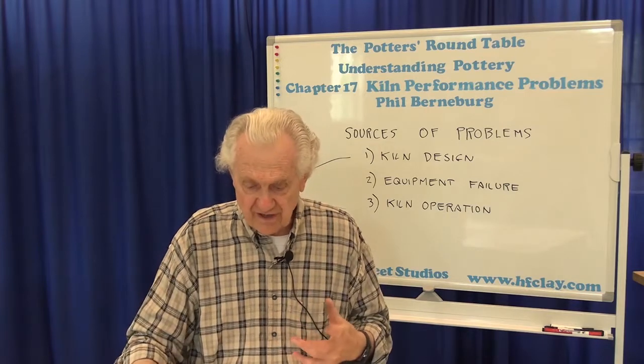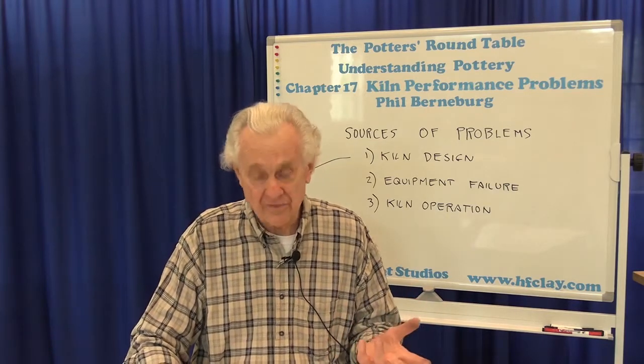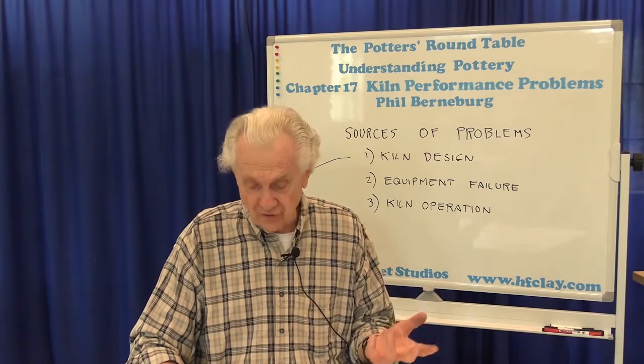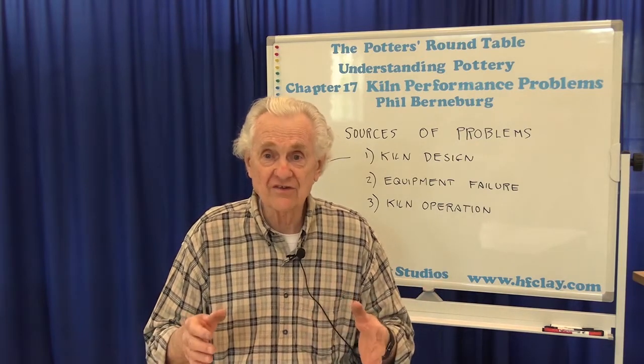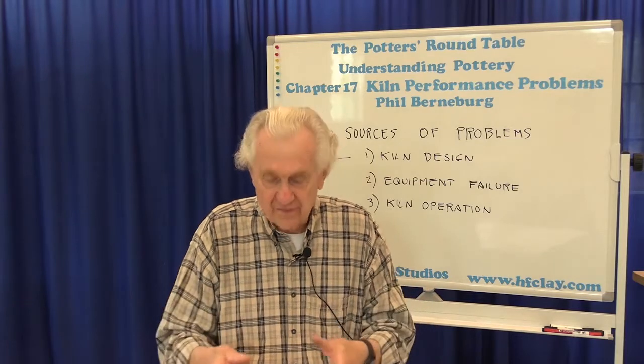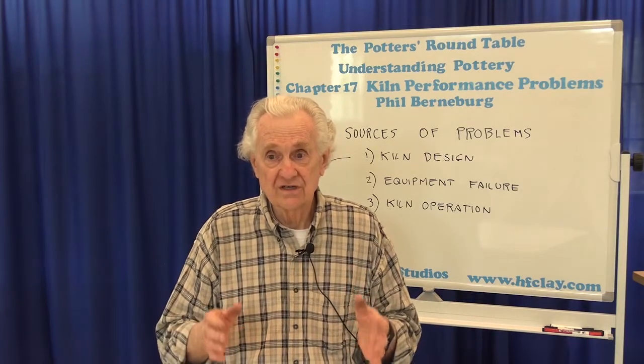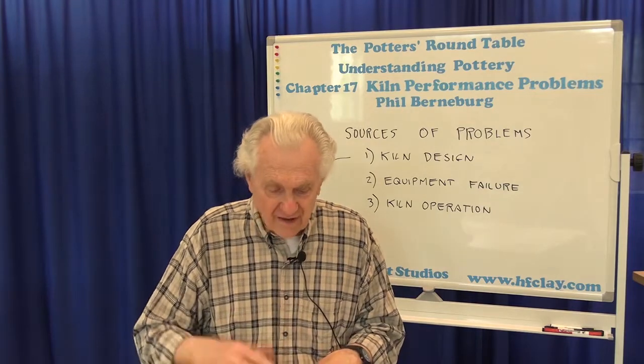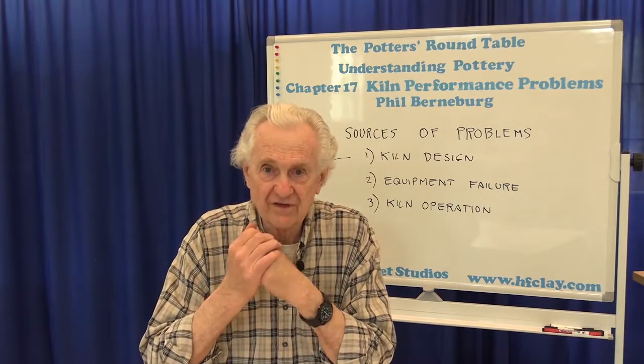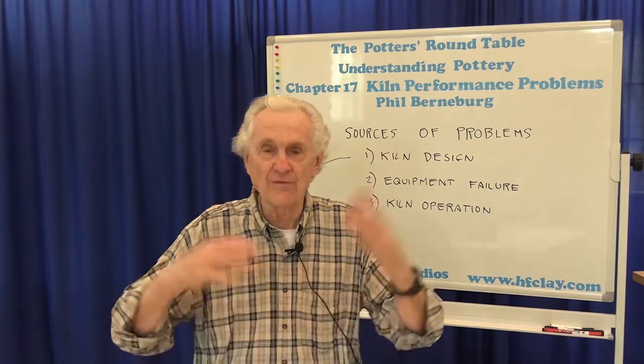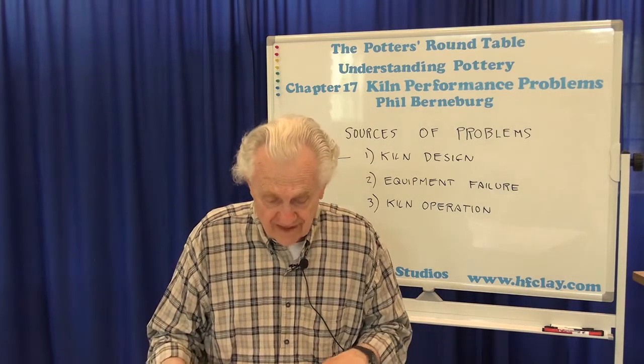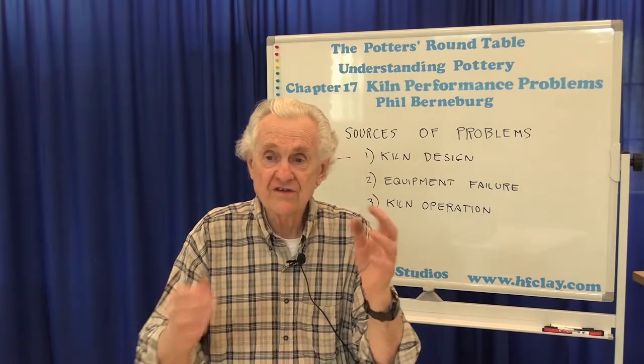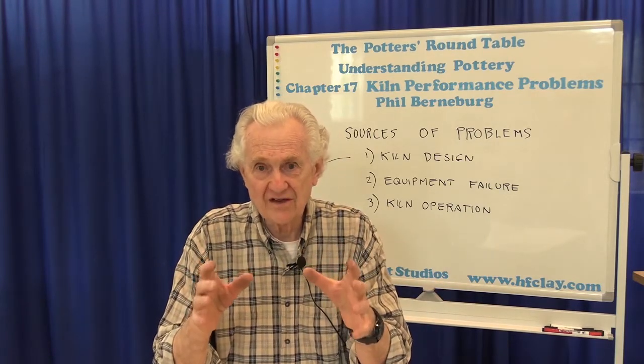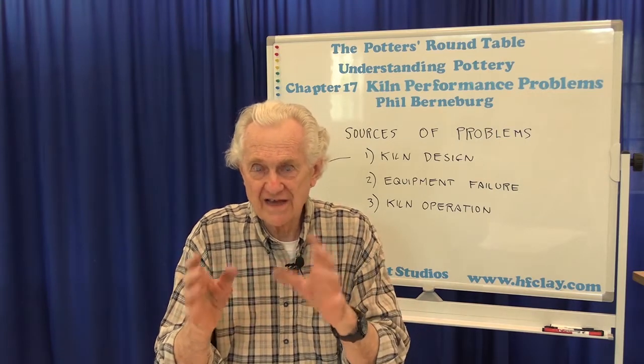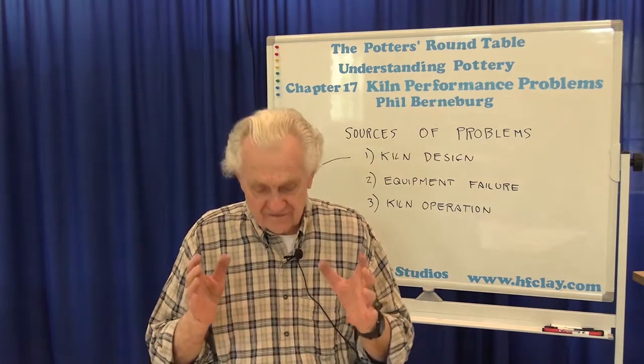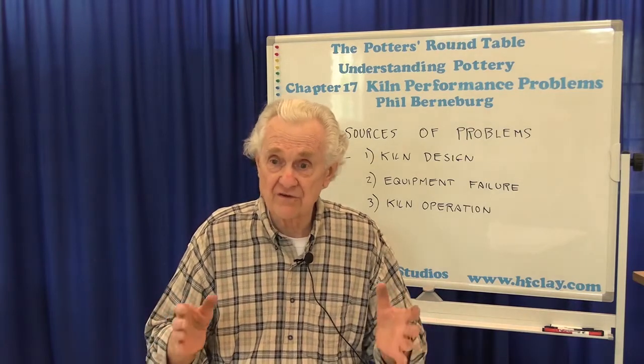And all the other things we talked about, the air inlets may be too small, the firebox may be too small, the exit flue may be too small, the chimney may be too short. It still comes down to, for whatever reason, and there are a lot of contributing factors, you're not burning enough wood fast enough. Okay, well then after the firing, you maybe have the problem of, yeah, I'm burning the wood so fast, I'm using an enormous amount of wood for the firing, I'm wasting wood. Well, this again is control. This is achieving the right balance between the right amount of fuel and the right amount of air and the right timing so that you're getting efficient burning. It's basically controlling the draft.